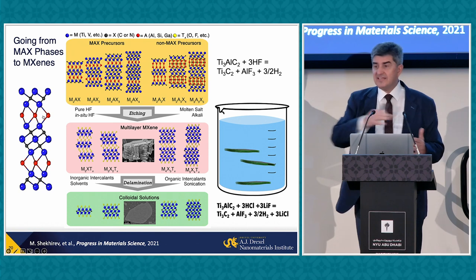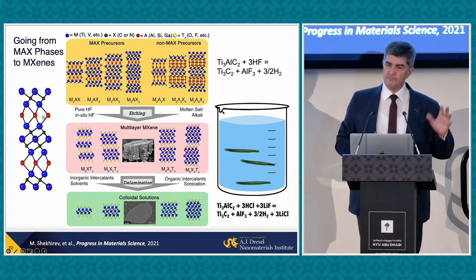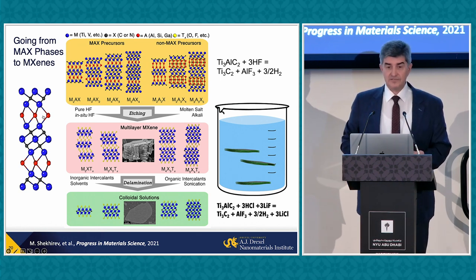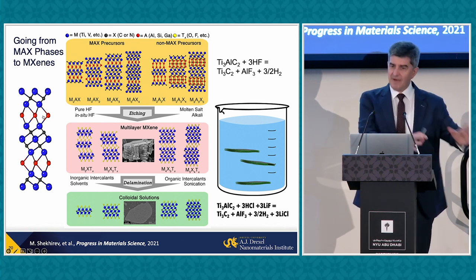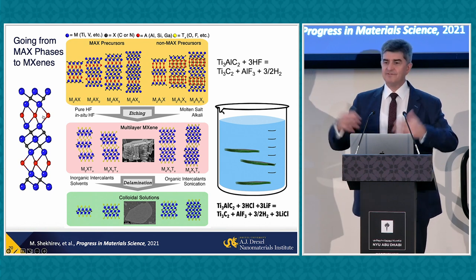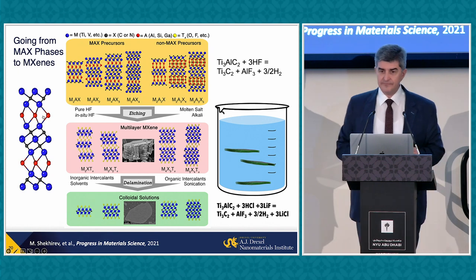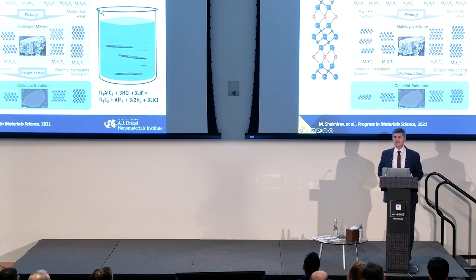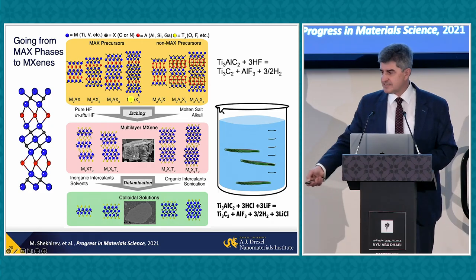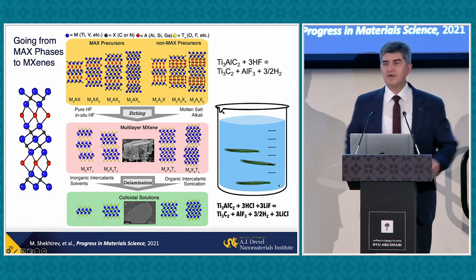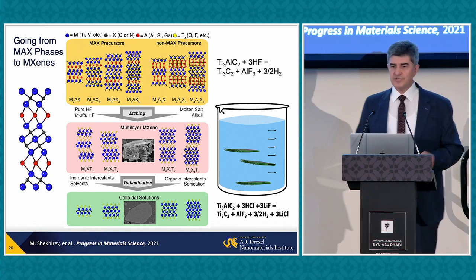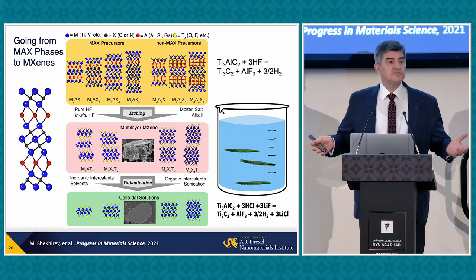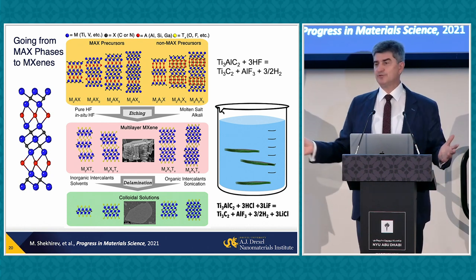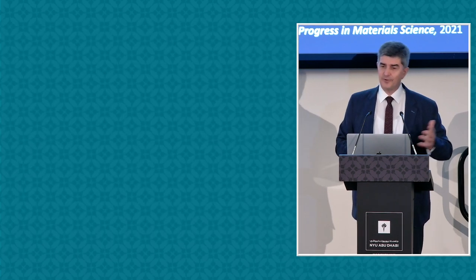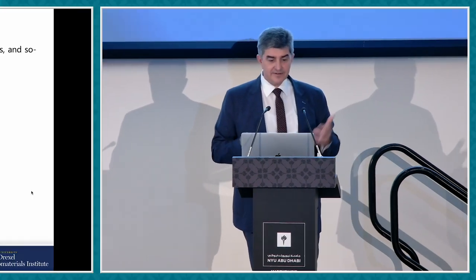So we thought, okay, maybe if we etch the material a little bit selectively as we did before for carbides to remove metals, we will make room for silicon. But we tried many solvents again. It means that Michael was going to the lab, coming back with another disappointment to us. We brainstormed with him and told him, try this, try that. Finally, he found that hydrofluoric acid can damage MAX phases, and he decided to try hydrofluoric acid. As a result, he got these layers, sheets that you can see in this picture after etching is achieved, initially here. And when he gave it to my postdoc to do microscopy, my postdoc, Junjie Yu, he's a professor now too, just like Michael, told me, you got graphene, because there were thin two-dimensional sheets visually very similar to graphene. But after he did more detailed analysis, he realized, no, it's not graphene, this is carbide. So basically, again, there is no warranty of success.